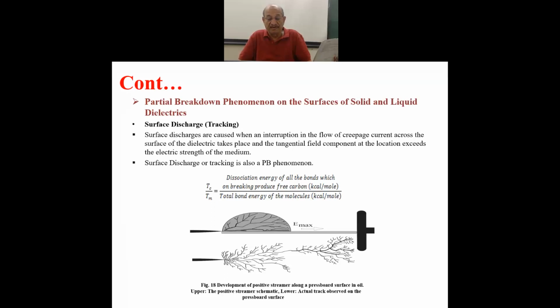So the needle is taken as the high voltage electrode. The potential is applied at the tip, on the surface of the solid dielectric, and on the right is the ground electrode. The surface breakdown phenomenon begins where Emax exists at the tip of the needle electrode, and the lower is the actual track observed on the pressboard surface.